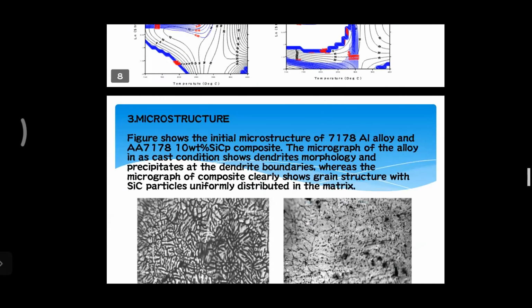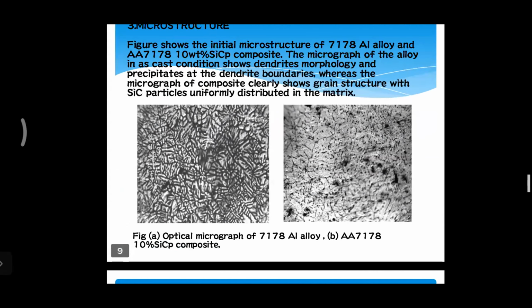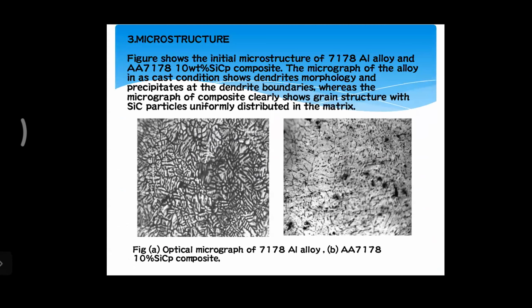In the results, I have discussed that the efficiency is almost 25 to 28% in different regions, but in the higher temperature region, above 250 to 400 degrees centigrade, we got the efficiency range. And the microstructure in the 4 different regions. These 2 microstructures are of the undeformed materials, the initial stage. The first shows the optical micrograph of 7178 aluminum alloy, and the second, B, represents the 7178 plus 10% SiC composite.